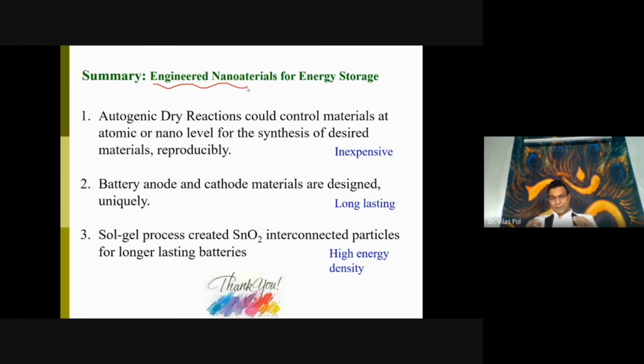Although the surface area was low, when you bring lithium back and forth, there is a little bit of expansion happening. The alloy tin forms with lithium is Li4.4Sn. And structurally, it is almost 300% higher, or three times bigger, when lithium reacts with tin. So we have to accommodate that expansion in some cavity. And that is why those cavities were purposefully created in the electrode architecture, where the lithium could come and expand in the electrode without expanding the whole battery. Within the electrode, it was happening locally. And then the battery charge and discharge could happen.